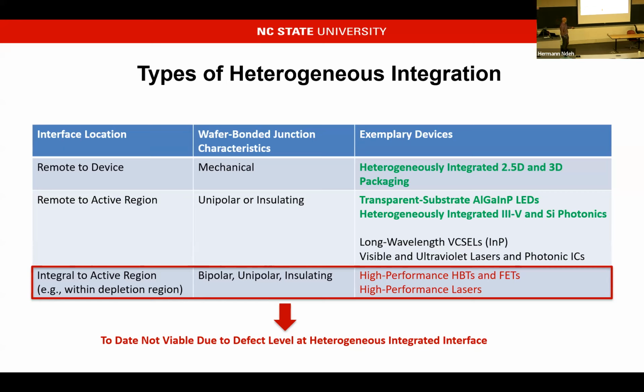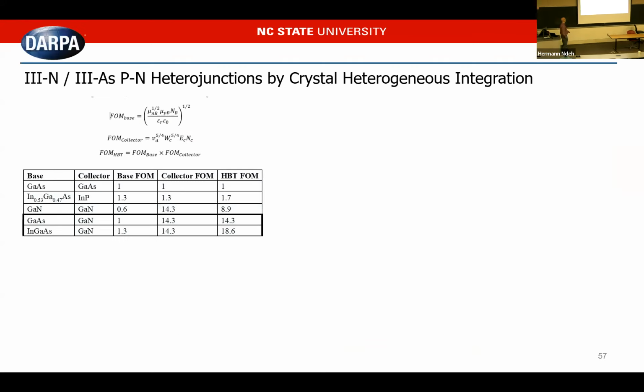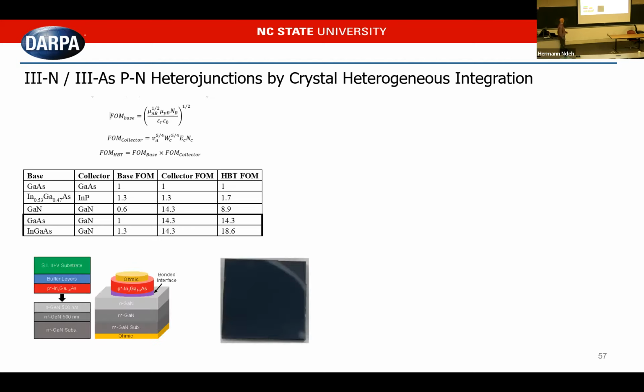The problem has been it's not been viable to date because of the high defect level. So the work that we've been doing in conjunction with Spiros's group and Zlatko's group has been, could we make an indium gallium arsenide to gallium nitride PN junction with low enough defects that would make a better HBT? The calculations that Spiros has done said that if you could do that, you can make an HBT that's substantially better than the state of the art that people use today, InGaAs indium phosphide, right? More than 10x better. So between our groups, we've been working to integrate these InGaAs to gallium nitride junctions.